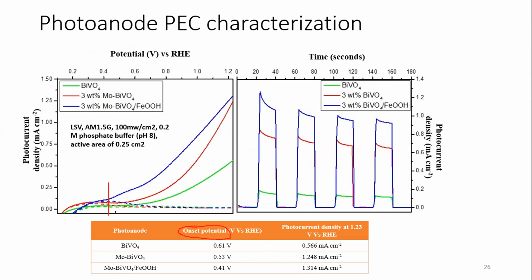For the photoanode, you look at where the photocurrent starts increasing up to 1.23 V, because here the oxidation potential of water is taking place. That voltage is roughly estimated as photovoltage, but this is not the exact way of measuring it. But you can roughly estimate how much photovoltage is generated by the semiconductor photoelectrode.